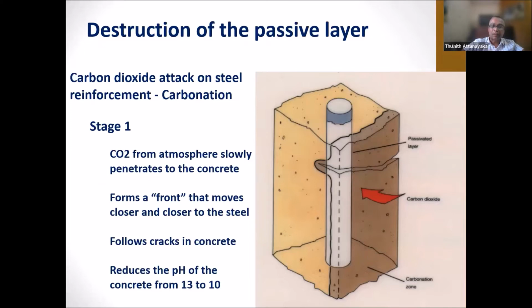That is carbon dioxide from the atmosphere slowly penetrates the concrete, because as you all know, even with a 0.1 millimeter crack, the chloride ions and other ions will get absorbed into the structure. So it's a front that moves close to the steel, follows through the cracks in the concrete, and it will reduce the pH of the concrete from 13 to 10. So now the pH value of the concrete is getting reduced.